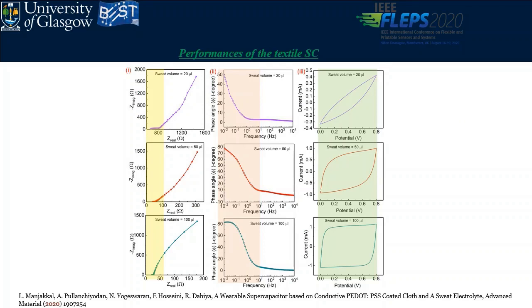You can clearly note that at 20 microliter, the device shows a charge transfer resistance, and you can see it from the impedance plot here, at almost 600 to 700 ohm. But when increasing the volume, the volume means the wettability. When the wettability of the electrode increases, the contact resistance of the electrode decreases. You can see that at 100 microliter the device shows excellent performance.